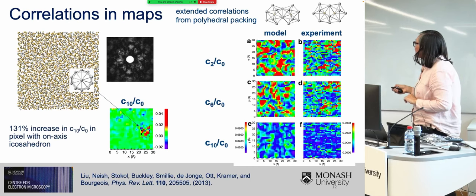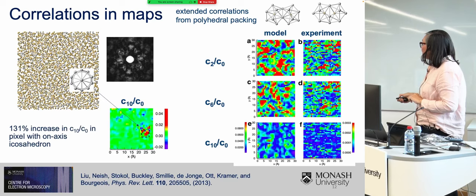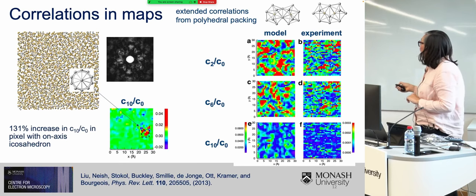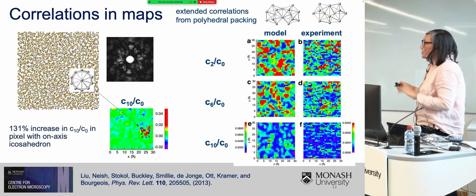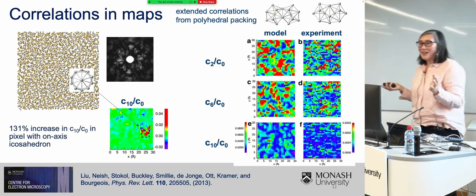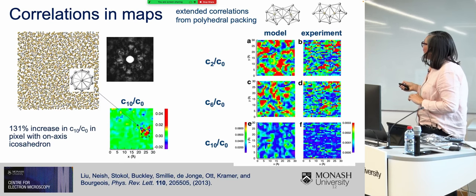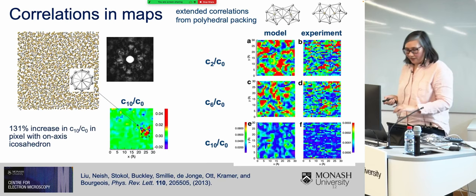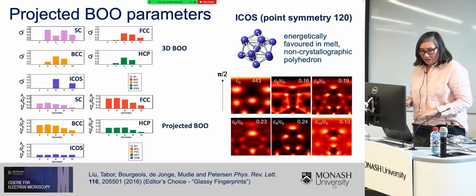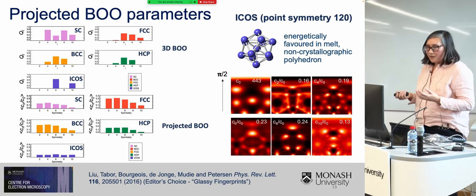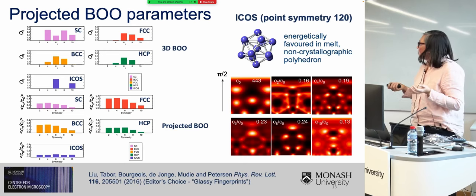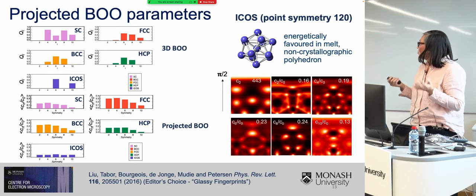Encouraged by this, I mapped out various symmetries for a metallic glass. This is my model, and this is my experiment, and you can see they compare quite nicely. I couldn't see any real extended correlations that other people had missed in my maps, which is quite nice. At most, if there were extended correlations, they related to either face sharing or interpenetrating polyhedral packing. But when I was doing this, I was somehow inspired to think, could I use these angular symmetries or order parameters in a more quantitative way?